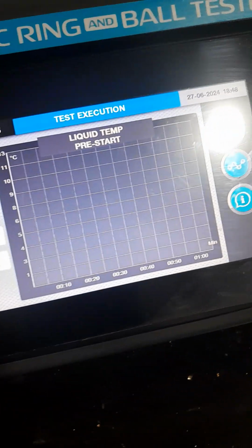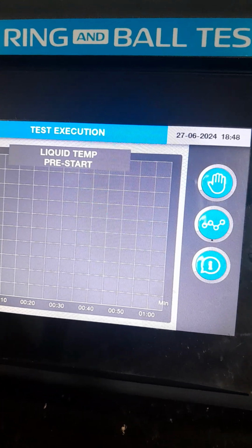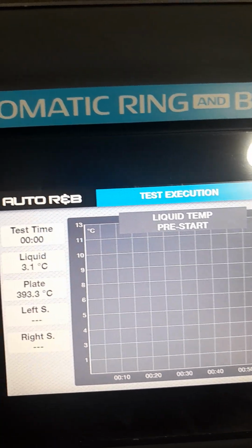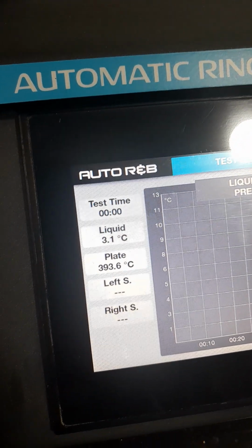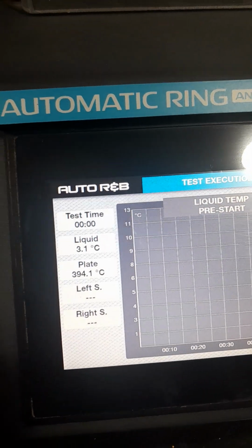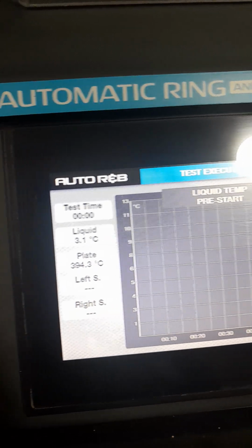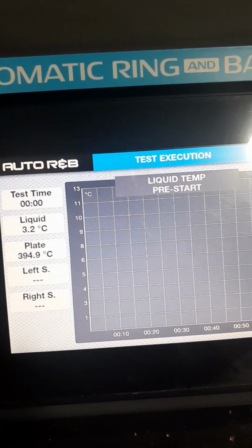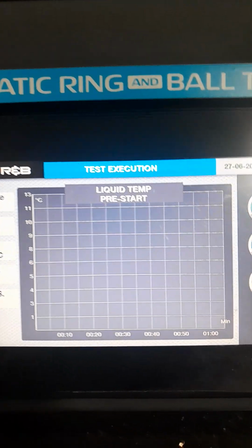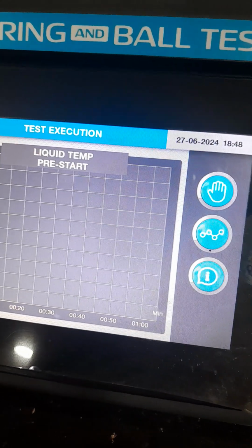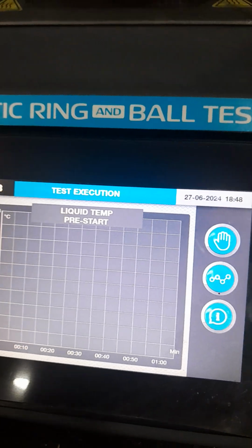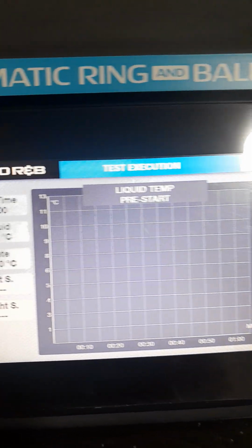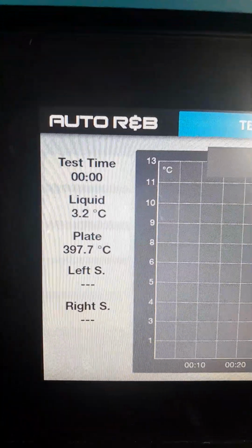So you get 162. So roughly, the bitumen can be heated at 160 degrees Celsius without any negative effect to its behavior, whether aging or rotting or weakening any of the bitumen composition before being added to aggregate for asphalt making. The temperature right now is 3.2 degrees Celsius.